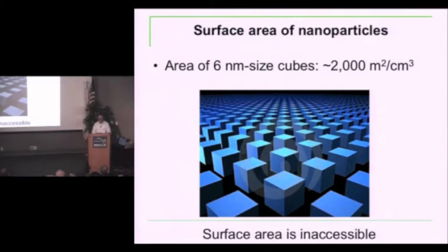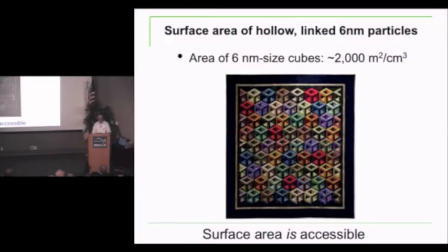And so what metal organic frameworks have figured out how to do to achieve this is to use hollow cubes and link them together. If you do that and you calculate the surface area provided by this scaffold, let's say the scaffold is based on phenylene units, you find that in fact you should get around 2,000 square meters per cubic centimeter.